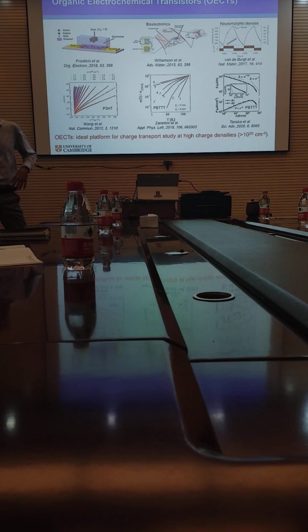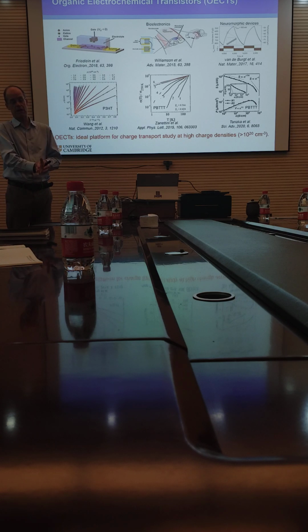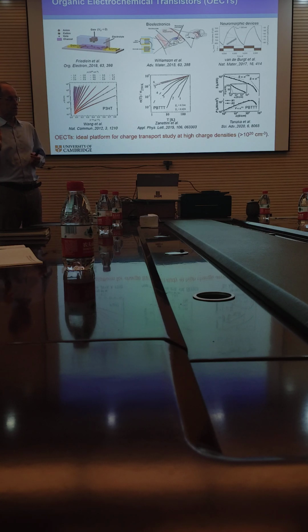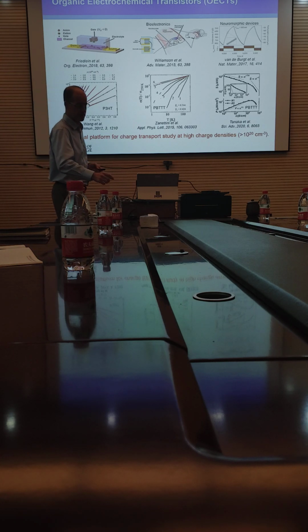For us, we also use OECTs just as a tool to study physics. If you want to study the phase diagram of the transport properties as a function of carrier concentration, you don't want to make 100 different films and measure them all. In an OECT, you can dial in a particular conduction state, do your transport measurement as a function of temperature, for example, then go to the next gate voltage, dial in a different conductivity, and study charge transport as a function of carrier density.